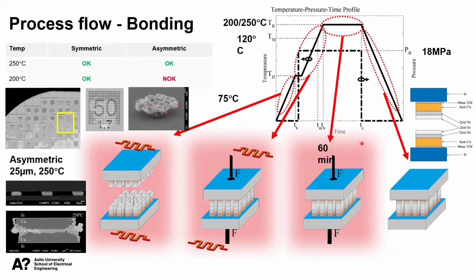In this test batch we had two different types of structures. The symmetric structure where copper, indium and tin were deposited on both wafers, and asymmetric structure where tin and indium was plated only on the cap wafer side. The bonding trials were mainly successful, so we were able to achieve high quality bonds down to 25 micrometer bump sizes and temperatures down to 200 degrees centigrade. However, there still remain some challenges related to the smallest micro interconnections, 10 micrometer interconnections and alignment marks. These challenges were our photolithography and etching processes.